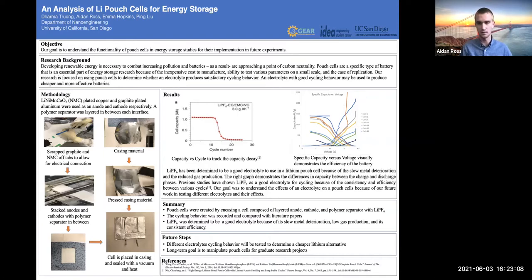And as you can see, the large orange line kind of on the right, that's our first cycle, and it has the most capacity. And as you increase the cycle number, the capacity decreases over time, as most batteries do. And as you can see on the left graph, which is data that is not ours from a paper, they also used lithium hexafluorophosphate, and their capacity stayed consistent and then dropped off quickly, most likely due to different parameters than we were using.